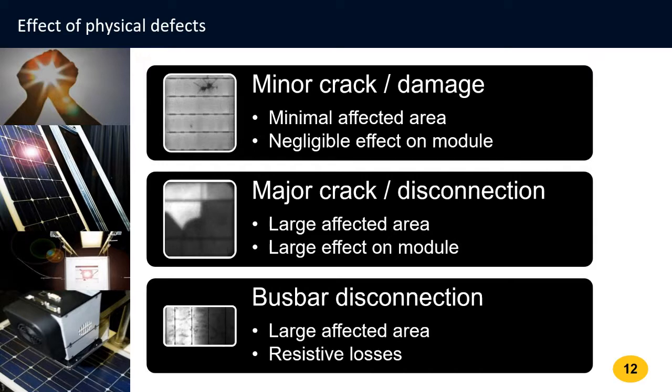Being dissipated within a single cell would obviously destroy it very quickly. That's the worst case scenario, but you have the ability to put a lot of energy into a very small area to create quite a hot spot. And there are modules that have cracked due to thermal stresses. There's such a thermal gradient across the glass that I have seen in the field the module shattering.